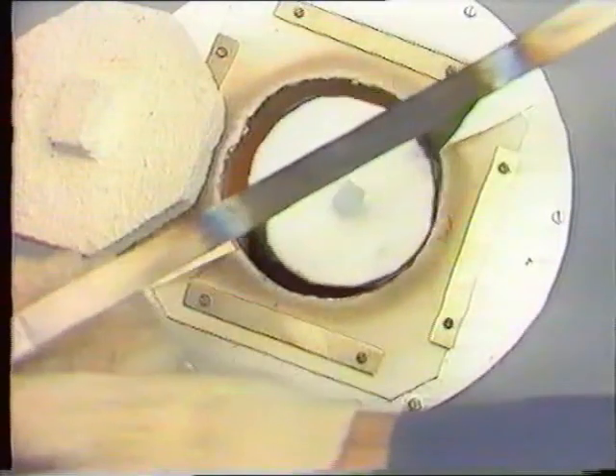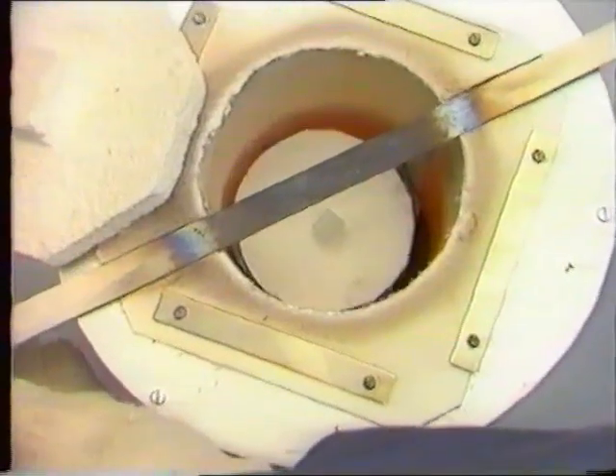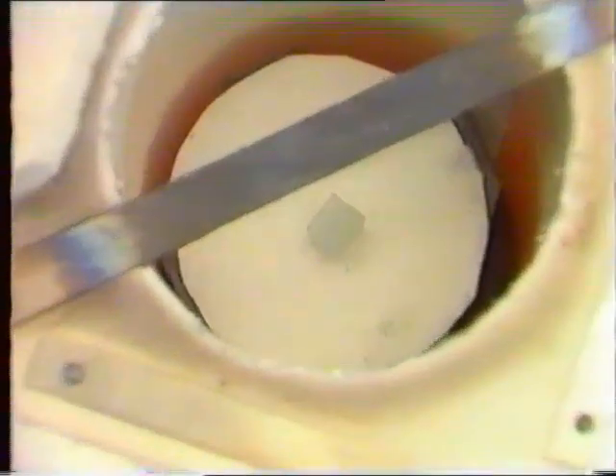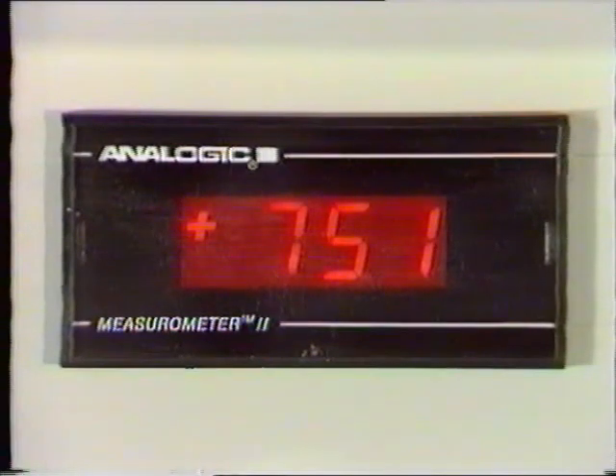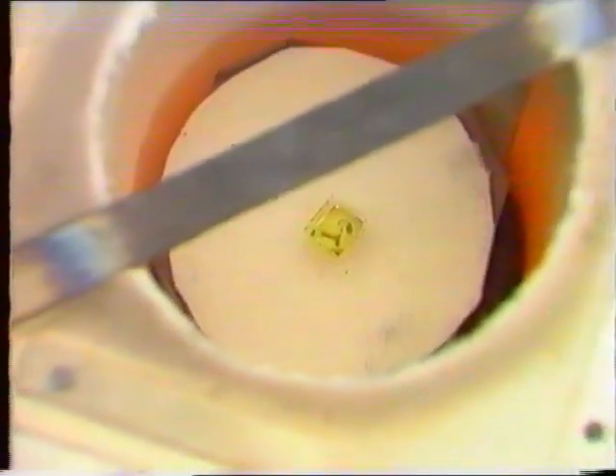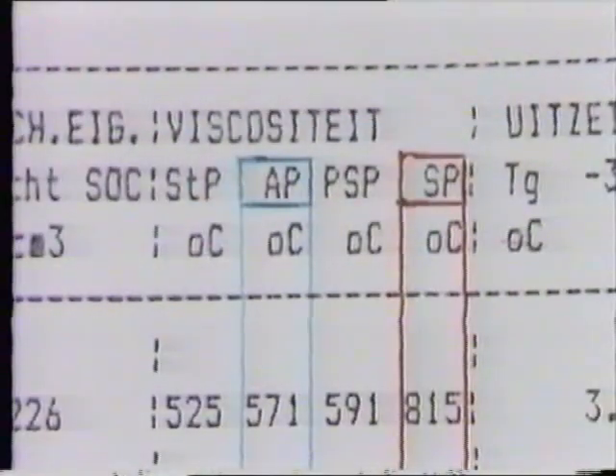The holder, with one or more combinations of samples, is placed in the temperature-stabilized furnace. Then, the furnace is allowed to return to its original temperature. Every minute, the cover of the furnace is lifted and the appearance of the mark at the bottom of the piece of production glass is checked. The moment the mark shows up, the seal between the sample of production glass and standard glass is complete.